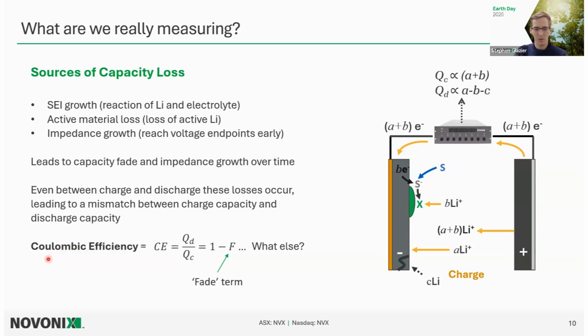So I'm going to build up this definition of coulombic efficiency a little bit differently than we are used to looking at it, perhaps. The definition of discharge capacity divided by charge capacity is commonly used. I'm going to state it a slightly different way to split up some of the different mechanisms that we can measure with UHPC. So we just mentioned that during charge, we may lose some lithium inventory into some of these different mechanisms. And on discharge, we don't get all of those lithium ions back, so we don't count as many electrons back. So we're going to introduce this fade term here, where our coulombic efficiency is 1 if our cell was perfect every cycle, and then take away this term that's due to these fade-based mechanisms.